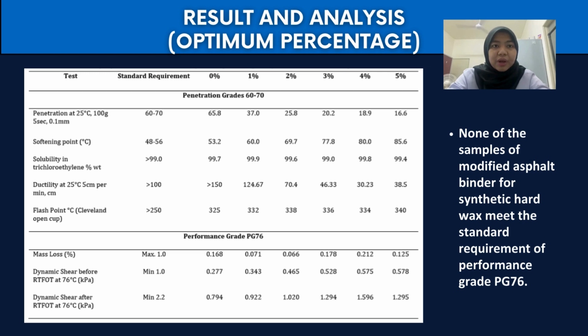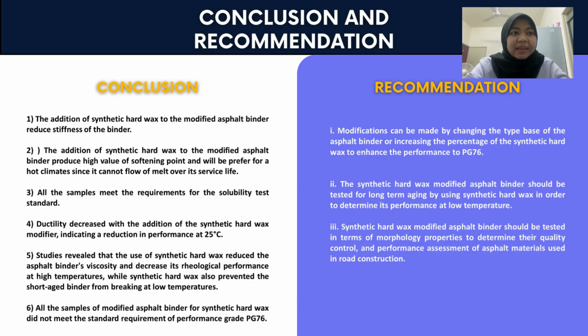This table shows how the optimum percentage of synthetic hard wax in asphalt binder is determined. It refers to the performance grade PG76 requirement. The results show none of the samples of modified asphalt binder meet the standard requirement of performance grade PG76. Last but not least, conclusion and recommendation.